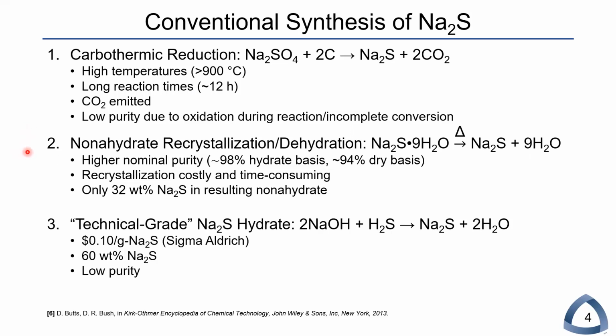There's a third route to a so-called technical-grade sodium sulfide hydrate, which is produced as a byproduct of a couple of industrial processes, primarily the caustic scrubbing of sour gases with a sodium hydroxide solution. This material is relatively inexpensive, about 10 cents per gram from Sigma-Aldrich, and has a higher concentration of sodium sulfide than the nonahydrate. However, its purity is typically inferior to that of routes 1 and 2.